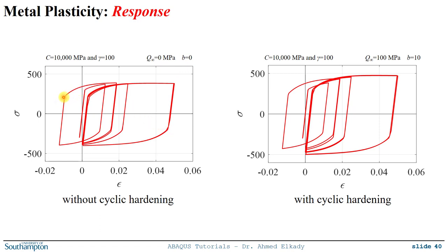By the way, you see here the plastic hardening part, this kinematic hardening part, you see how it goes. It's curved like this. If you reduce the value of gamma, you will start getting a more linear hardening behavior. On the right, we see the same model, but in this one we put cyclic hardening. So you put Q infinity of 100 megapascal and B equal to 10. And you see here in the same model, you reached higher stresses with increasing plastic deformations because the size of the yield surface increased. By how much? Actually the maximum would be 100, so if we started at 300 you would see that the maximum that you would reach would be around 400.